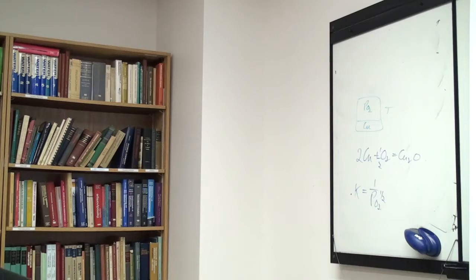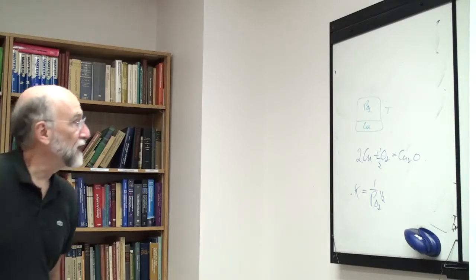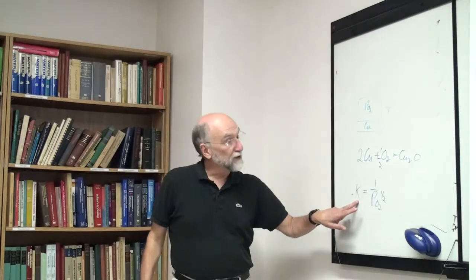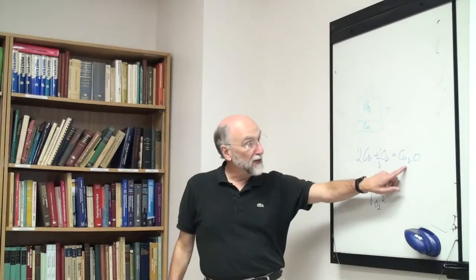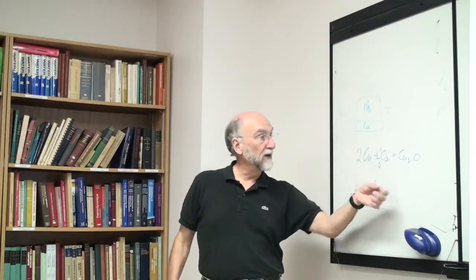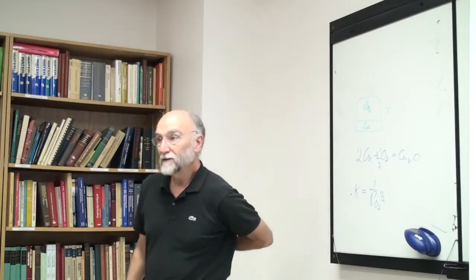As you take copper solid and increase the temperature, at a certain point the solid melts to form liquid. This is the melting point, and so on. If you were to take a constant pressure of oxygen over Cu2O and increase the temperature, at a certain point the Cu2O would dissociate. So now you're taking this reaction, the equilibrium constant is changing as you change the temperature. As you heat it up and heat it up, the reaction tends to go more and more to the left, and eventually it dissociates.